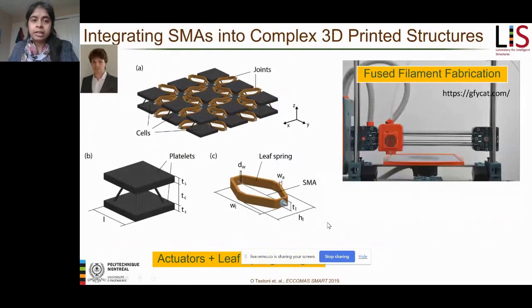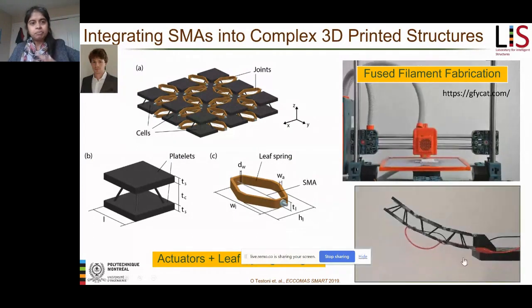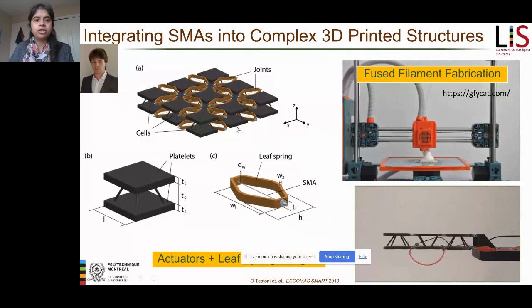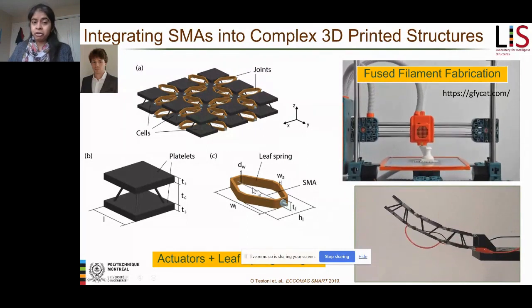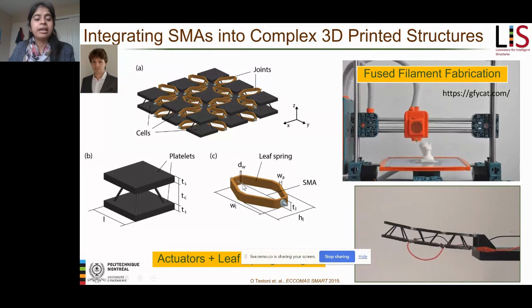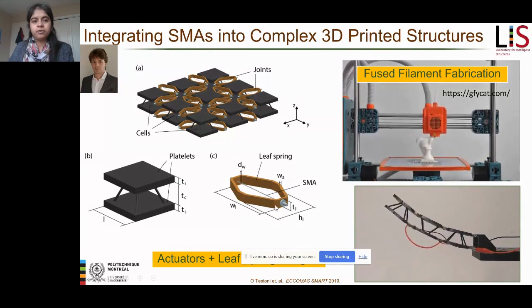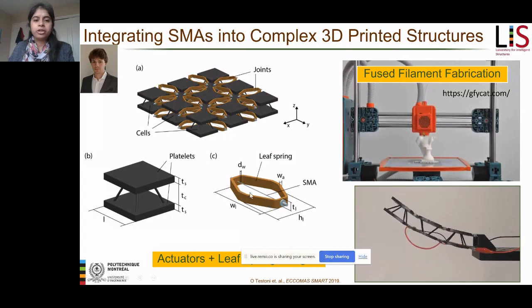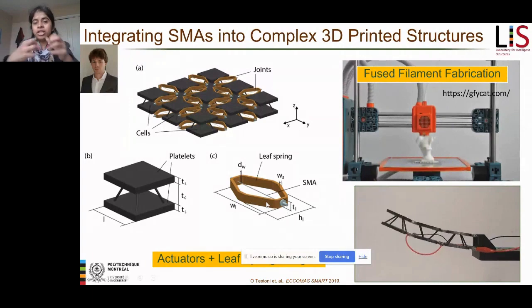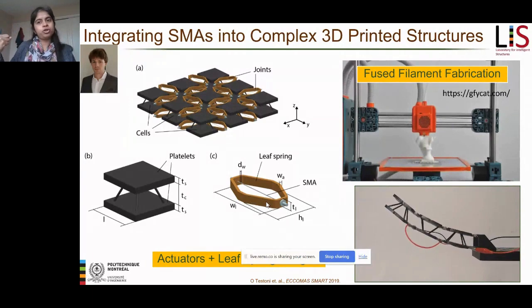So during my postdoc at ETH Zurich, this was the PhD student I was working with, and he was trying to design these panels that can change their shapes. What he was doing was using shape memory alloy wires in leaf springs that were designed using PEEK. These are the leaf springs that are printed with PEEK. The advantage is that when the shape memory alloy is heated, it contracts. So you have a shape change. And when it cools down, the leaf spring brings it back to its original shape. So you have a one-way alloy, but you have a two-way effect upon heating and cooling the structure.